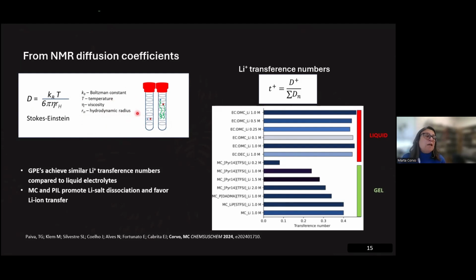Because of this, we can get the diffusion coefficient for each of the species in our solution. And from these diffusion coefficients, we can get the transference numbers. We did this for lithium, and the transference numbers for lithium for all of our gel polymer electrolytes that were prepared with methyl cellulose are here. We also have done the same with the commercial electrolytes with ethylene carbonate and dimethyl carbonate, with lithium, all of them in similar concentrations.